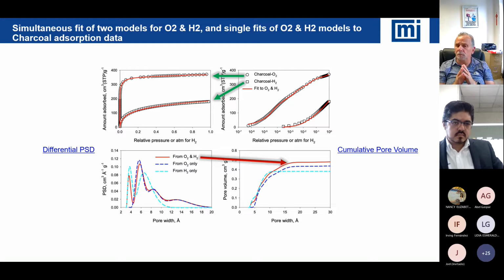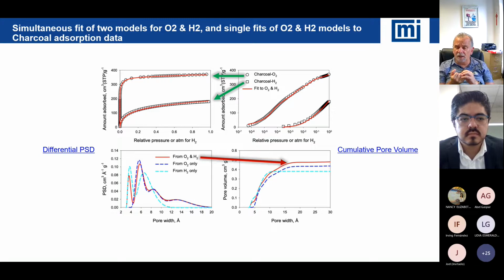It is much more difficult to measure a pore size distribution on something like a pelleted zeolite than a powdered zeolite. It's much more challenging and takes much more time. If you start off with 13X pellets, it could be 5 to 6 days to get a high resolution isotherm. If you powder it, it's on the order of 2 to 3 days or less. Again, removing the heat can be challenging, and also you will get into some diffusion limitations. But going from the outside of a particle to the inside of a particle with the gas phase is on the order of seconds. So the diffusion limitations really get back again to the micropore size of things. Removing the heat becomes very challenging.